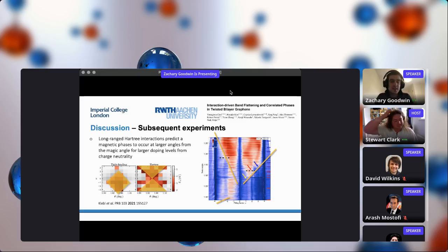And the other effect is actually from screening. In a DFT calculation, you do something in vacuum and there's no additional screening. But on a substrate, you have screening from the HBN and actually the backgate, which dopes the material. But we found that these Hartree interactions are really quite robust to the dielectric environment. So we can use a metallic gate screened interaction, or we can have a dielectric constant of 4, which models hexagonal boron nitride, and the effects are really quite small on these Hartree interactions. Okay, yeah, thank you.